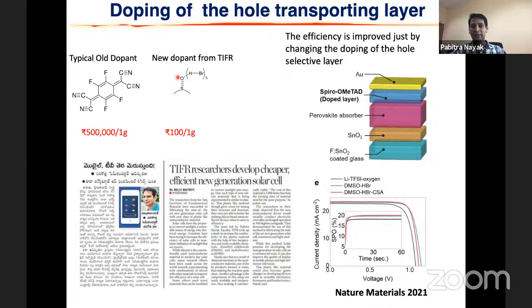You use a material called dimethyl sulfoxide. It is a very cheap organic solvent, and this hydrobromic acid. Individually, they don't do anything. But when you bring these things together, they start to increase the conductivity of the semiconducting materials used in this system. Not only that, if it doesn't do anything, there's a self-destruction mechanism already built into that thing.